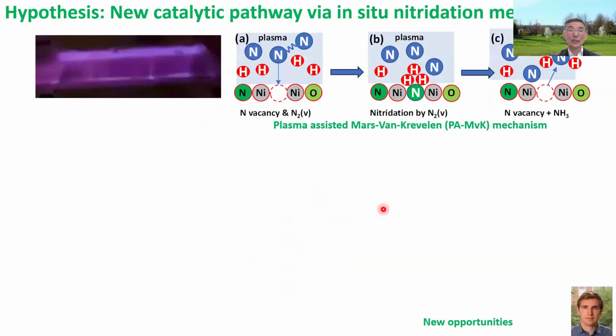So then I tried to propose a new idea. In a plasma discharge, when you have N atoms produced, vibrational nitrogen produced, the catalyst has a defect, a vacancy. Once the vibrational nitrogen sees the vacancy, it comes in and generates a nitride. The catalyst now goes from nickel to nickel nitride. I call this the plasma-assisted Mars-van Krevelen mechanism, PA-MvK.